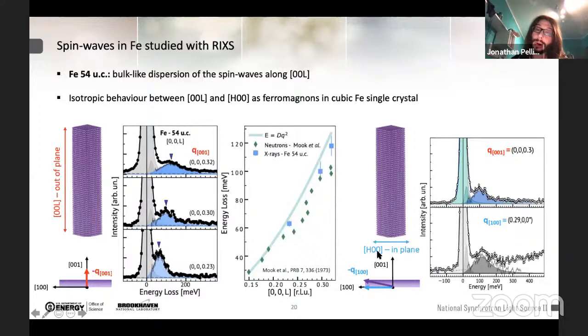In order to prove this, we also changed the direction of in-plane momentum transfer, and we compared the measurements between a 00L direction versus an H00 direction. Here I'm showing the RIXS spectra that we collected, and as a function of momentum, they look pretty identical in terms of spin excitation energy.